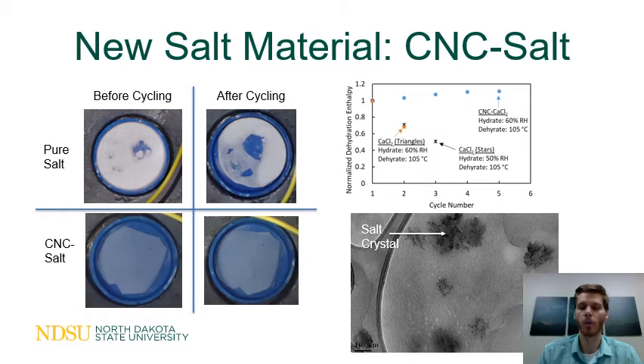Look at this. One way that we're approaching stability is by developing a new salt material. You can see up here we have the pure salt, and then we cycle it in a hydration chamber. This is before the hydration chamber, and then we send it through some cycles, and this is after. You can see how it's agglomerated and stuck together, and that reduces the energy density.